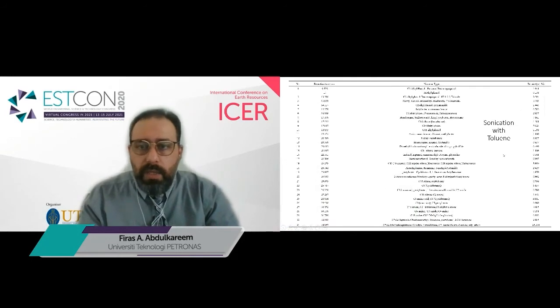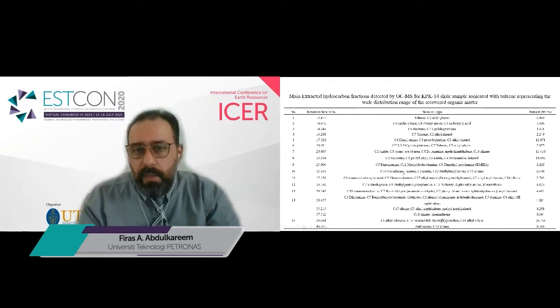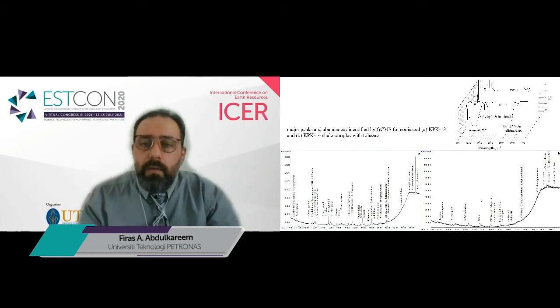On the other hand, with the sonication herein, we can see that the extraction also shows more or less a wide range of hydrocarbons extracted, somehow higher compared to the hot reflex, with some more hydrocarbons extracted up to C28 or C30 even. So that's somehow doubling the amount of extracted organic matter and heavy hydrocarbons compared to the hot reflex, which proves that ultrasonication assisted extraction, even using the same solvents, can enhance the extraction of the organic matter and heavy hydrocarbons from the shell compared to the hot reflex process.